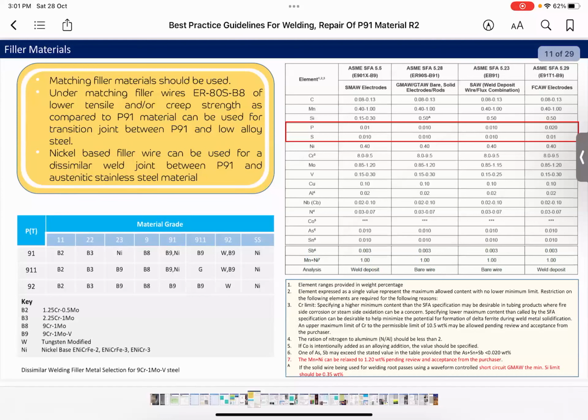Manganese and nickel should be limited to 1%. If it is to be exceeded, if it is to be higher, this should be approved by the owner or the purchaser. Also for short circuit GMAW, the silicon limit should be 0.35 or higher. This is because if it is less, it will affect the wetting action of the filler wire and creates many problems of lack of wall fusion.